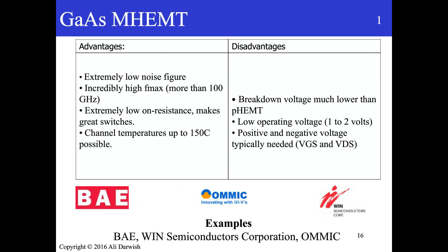For gallium arsenide MHEMT, it's kind of cheating to say that it's gallium arsenide, because it's essentially indium phosphide grown on gallium arsenide. So it's an attempt to lower the cost of indium phosphide by growing it on a less expensive substrate, and it offers, of course, extremely low noise figure because of the incredible gain it has, and the FMAX can go into the 100 gigahertz region. The disadvantage is that the breakdown voltage is low, and that means that we cannot handle very high power, and we still need the negative supply.